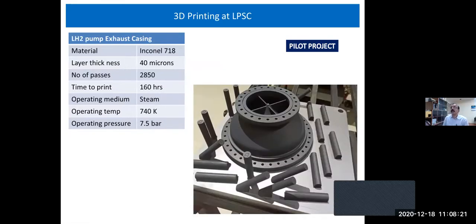And this is yet another one. This is made of Inconel. We've been choosing certain materials that could be printed: aluminum, steel, high nickel alloy. Inconel is a high nickel alloy. The layer thickness is 40 micron and 2,850 layers. The time to print is again 160 hours. Here the temperature is very high, 740 K, with an operating pressure of 7.5 bar and an operating medium of steam.